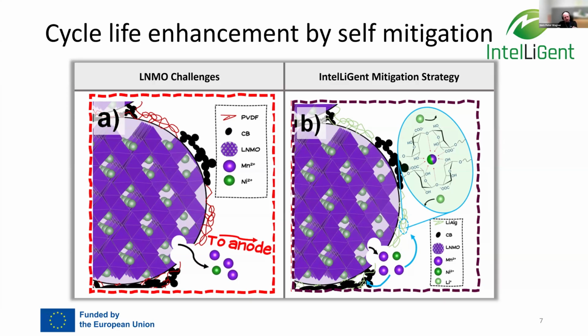So here we look at an LNMO cathode, and we are all quite aware of the challenges working with high voltage materials and also working with cathode materials in general that contain manganese. As chemists, we all love and hate manganese. It's a very nice and green element. The problem is that the 2+, the divalent state, is highly soluble in electrolyte. So in LNMO's case, both manganese and nickel can leach out from the cathode. They will reach the anode, and in short words, they will poison the SEI. So they will electroplate on the SEI and cause more side reactions in the cell.